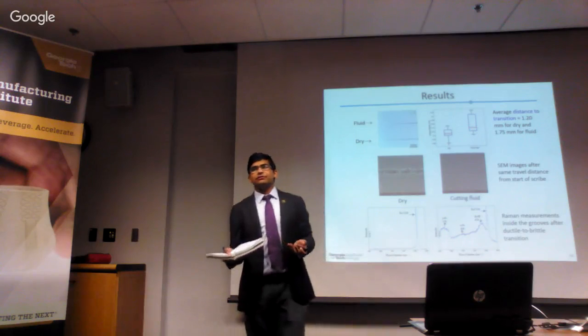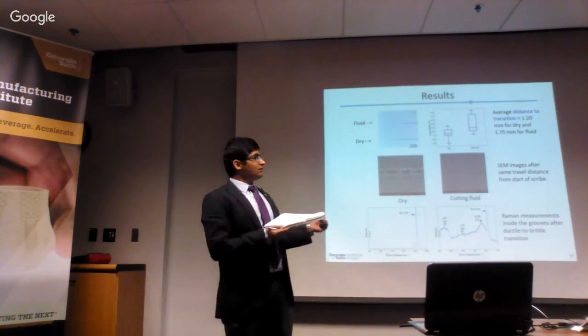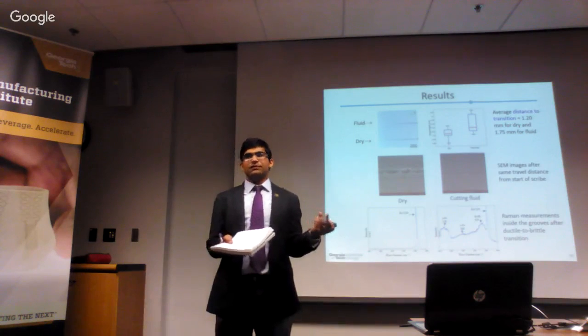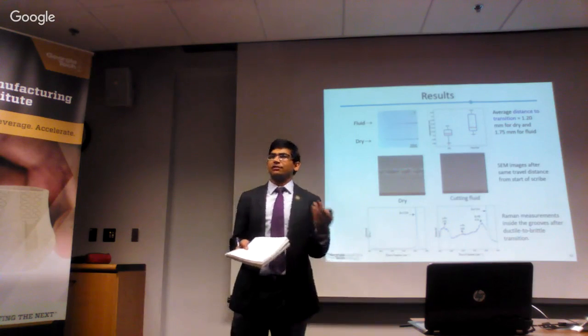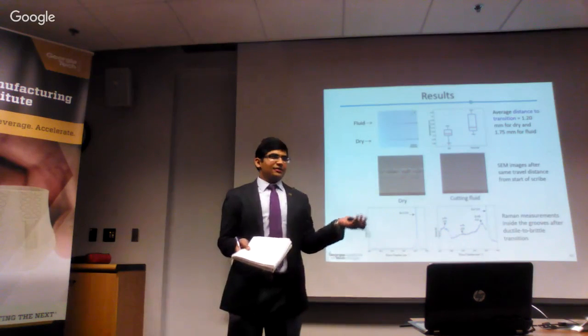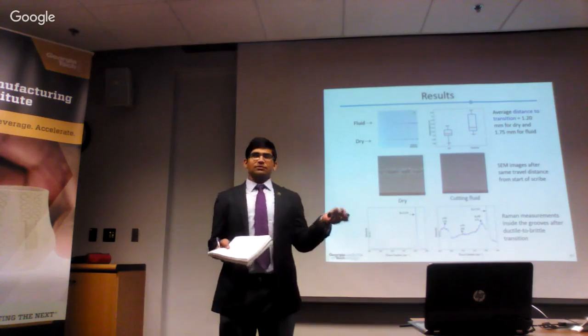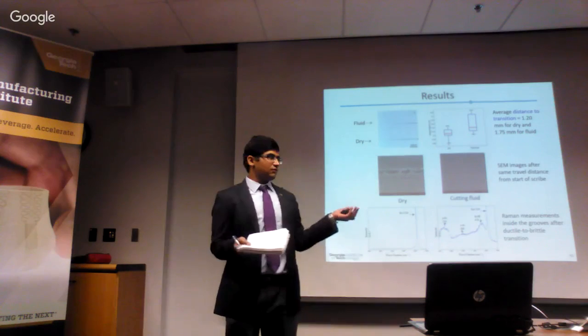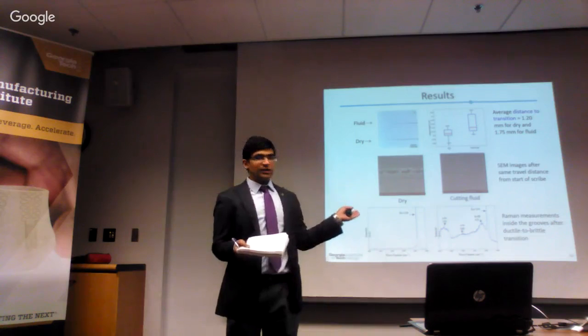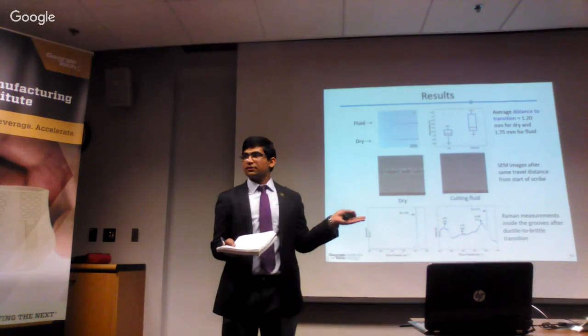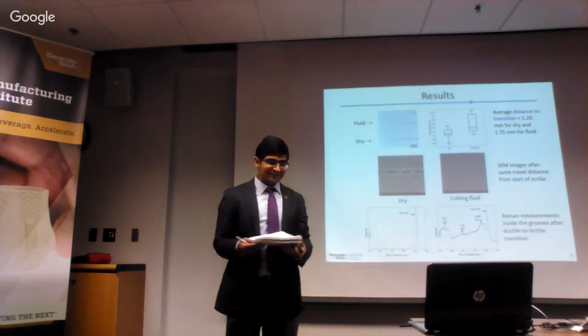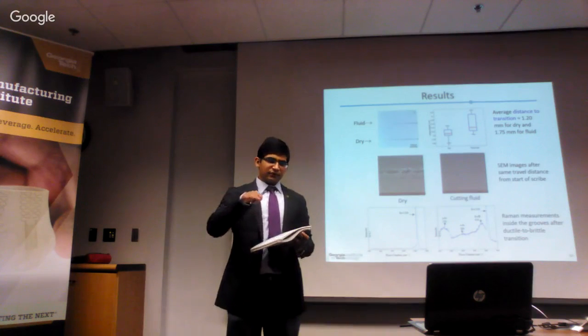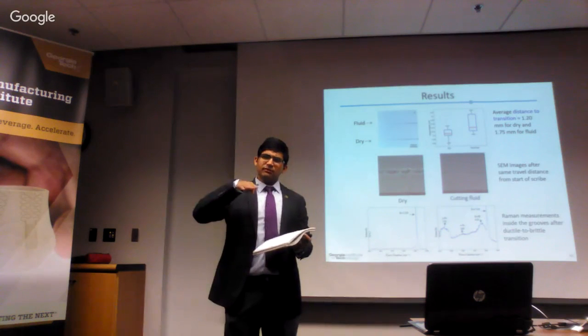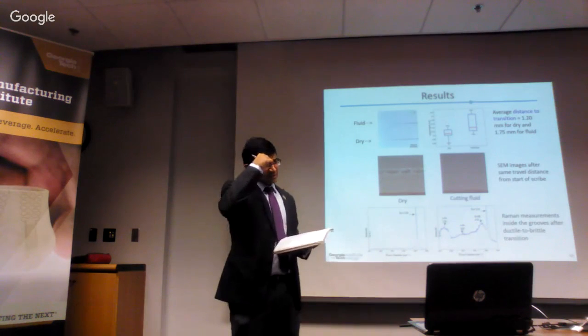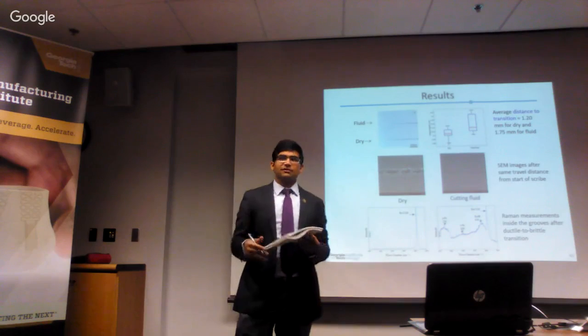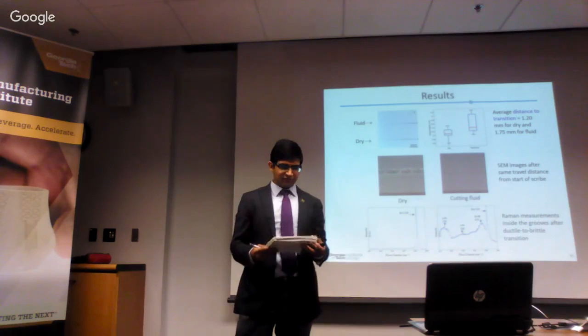Sure. So in all these experiments, we have the force dynamometer capturing the forces. So we have the tangential force and the normal force. Sorry, not average. We take the normal force over tangential force to get mu, the friction coefficient. Sorry, normal over tangent, the opposite way. Tangential over normal. And that's how we found the friction to be remaining almost the same over the two cases, not significant over the different experiments. There might be some difference, but not statistically different.